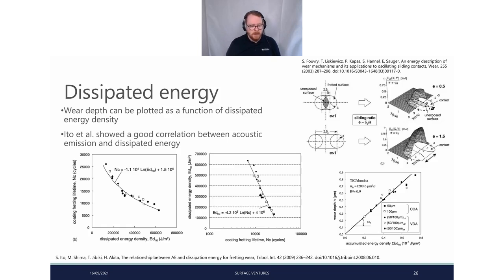So dissipated energy. This is a technique used in a lot of Fouvry's papers. So we have our little diagram up in the top left there. If we think of our fretting surface, so we have our sort of Hertzian contact that is moving. We have our unexposed surface in the middle. This is our more fatigue-driven part. Our sliding ratio. So essentially, we can think of this in terms of there's an amount of energy that is expended within this contact. The longer the fretting wear goes on, the more energy there is there. The more tangential force you apply, the more energy you're going to have as well.